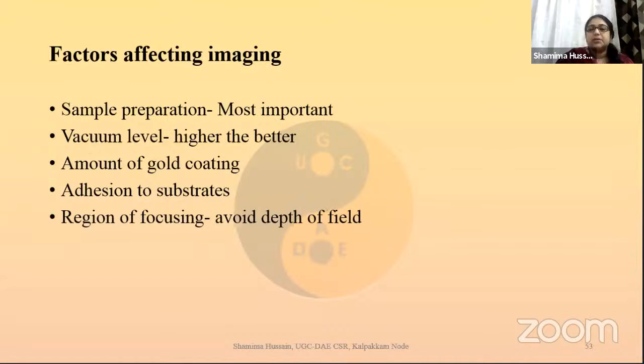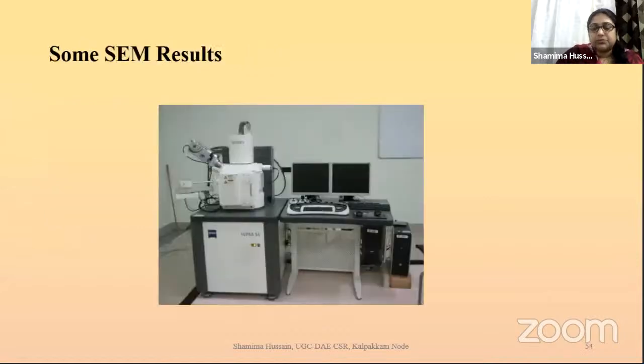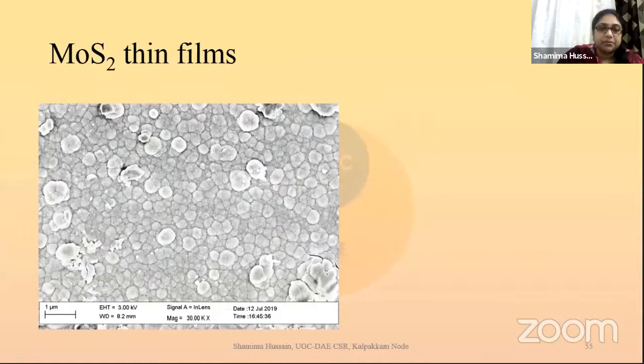And these are the other things which might affect the imaging. Sample preparation is very important. We should have a very high vacuum level. Gold coating, as I said, we need to have the sample surface conducting. That doesn't mean we just coat it with too much gold. Too much gold will just suppress all your features. So we need to have a very adequate amount only, which is usually we do a sputtering onto that, and it will be about 2 to 3 seconds, a maximum of 4 seconds. That's good enough. Depends on what voltage you're doing. That also is there. This is the SEM which we have at our institute, which we are using frequently, and the results that I've shown are from this system only.